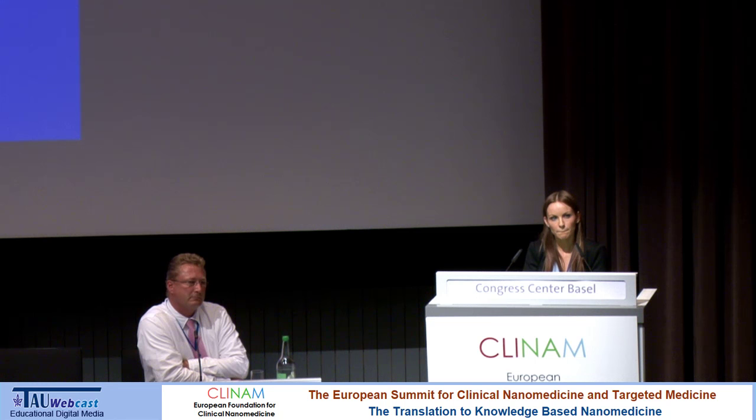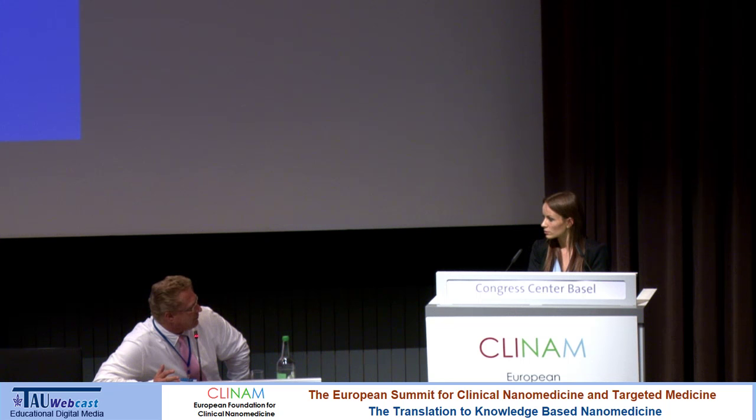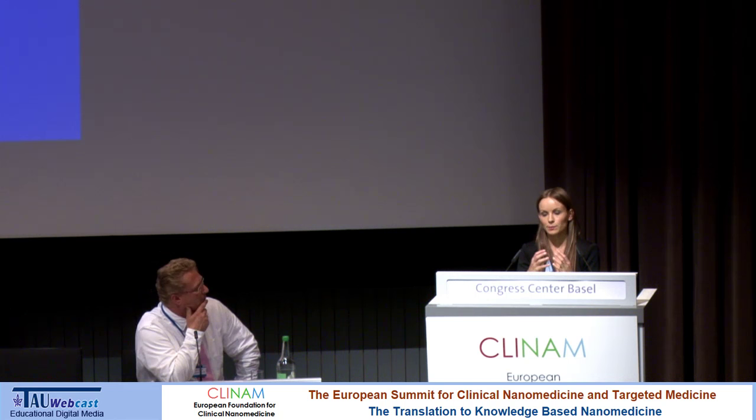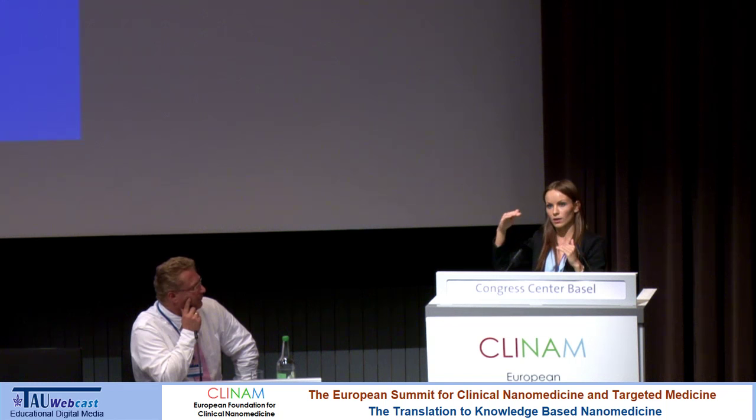Does this disintegration happen in the intravascular system or after, because in my mind it has to happen inside the blood? Yes, it happens inside the blood. Could you then perhaps even live without the silicon particles — what happens if you give simply the arginine and PEI? Then you have increased toxicity — that's your problem. I think also the biodistribution will not be as good. It's a biomimetic approach: we're utilizing the shape of platelets. The particles marginate against the blood vessel wall, while spherical particles tend to be in the middle of the vessel like red blood cells and don't interact with the actual endothelium. But if you have this disc shape, it's going to slide against the endothelium, increasing the chance that it will attach, and especially in inflamed endothelium you're going to have these kinds of interactions.